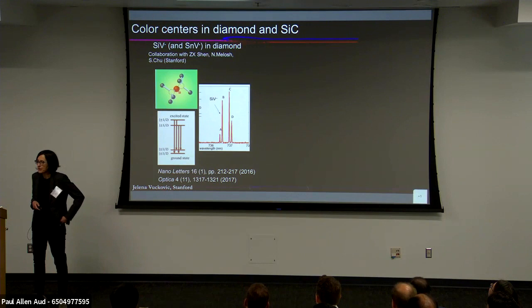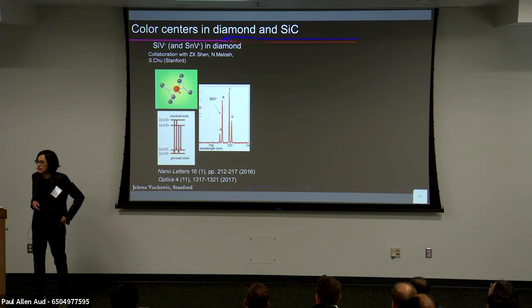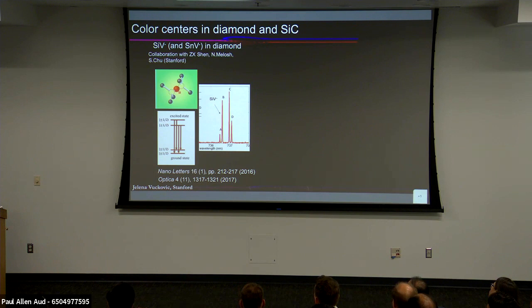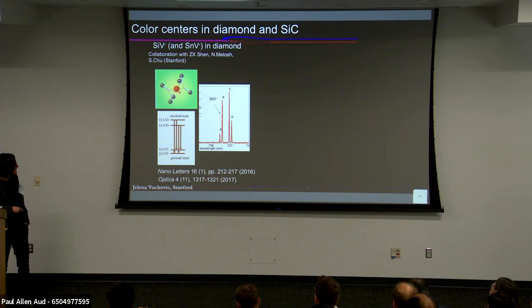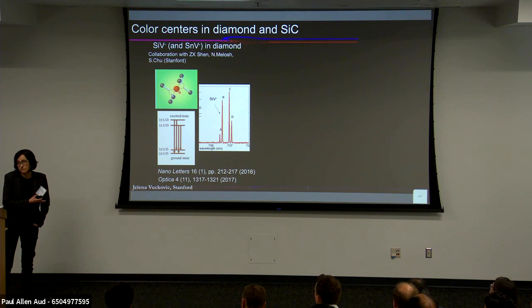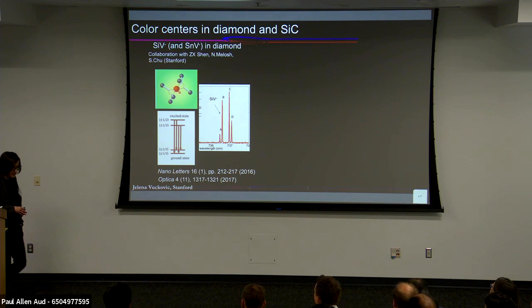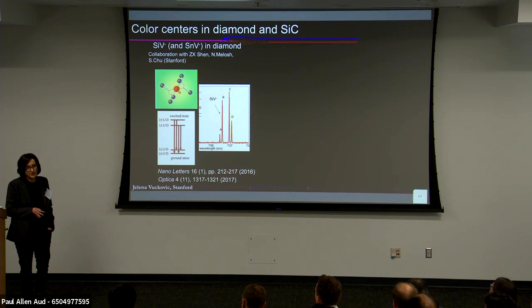Regarding homogeneous qubits with good optical interfaces, we're working on color centers in diamond and silicon carbide. In diamond, we're looking at silicon vacancy and tin vacancy — two missing carbon atoms with an extra silicon or tin atom in between. This is the energy level structure, and this is the spectrum for a single color center at low temperature. We work at around four Kelvin in closed-cycle cryostats — no dilution refrigerators needed, though you still have to cool the system to increase coherence times.